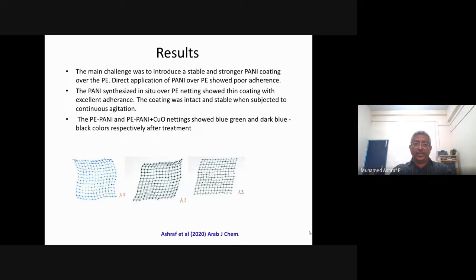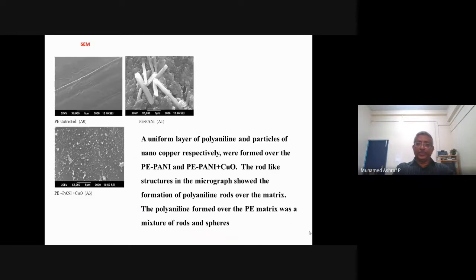And then what we have seen is that the polyaniline was very nicely accommodated over the net, and it is ready for the direct application of nano copper oxide. So a net with the polyaniline, you can see here A1, and then the polyethylene, polyaniline plus nano copper oxide is in A3, you can see in the picture. This was published in 2020, and we have taken scanning electron microscope images of this treated material. You could see a lot of polyaniline nano rods formed over the polyethylene net, and after treatment with nano copper oxide, you can see a lot of small islands of nano copper oxide.